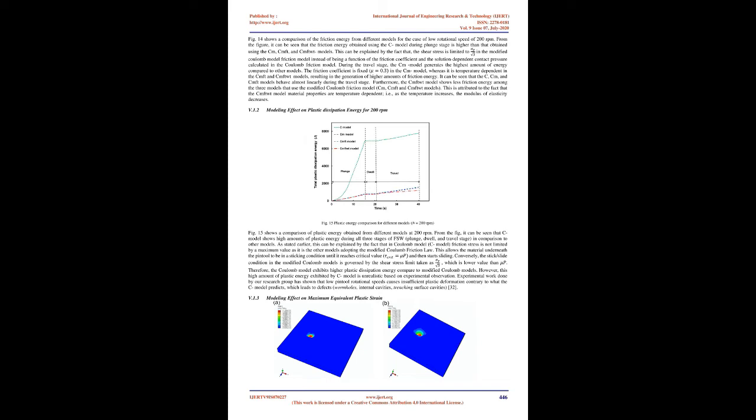This deviation can be explained by the fact that material properties of the workpiece are not temperature dependent and that the friction coefficient used in these contact models is constant rather than being temperature dependent. Temperature profiles obtained from CMFT and CMFTWT models show closer results compared to the experimental temperature result. Again, CMFTWT model results are the closest in comparison to experimental temperature profile. Comparison between the temperatures obtained from the FE models and from experiment along transverse direction is also listed in Table 5.